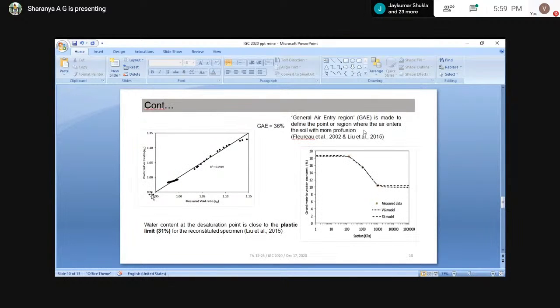And another major determination from this soil shrinkage curve is the general air entry region. That means the point where the air starts to enter into the soil phase system, and thus the volume change is induced. So here from the graph, the general air entry value is obtained to be 36%, and this value seems to be always close to the plastic limit of the soil. And for my samples also, I have got similar results, and this is in coherence with the findings of Liu et al. in 2015.